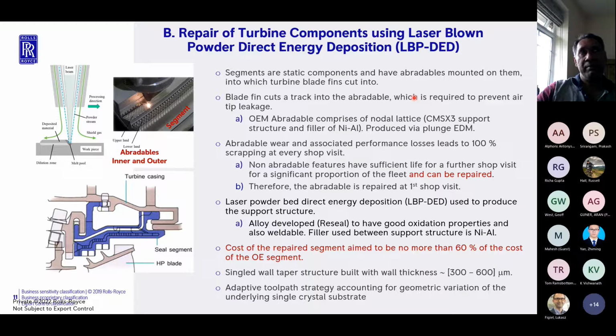So seal segments are typically components that are static. So these do not rotate like turbine blades. And really the main function of a seal segment is that the seal segment has got an abradable. So if you see a schematic diagram that I have here, this whole structure is the segment, and this is a blade. So the blade actually extends further down, but these two protuberances are the tips or the edges of the turbine blade. So these blade fins cut into the abradable. So this is one abradable, that's the other abradable, and these blade fins cut a track in the abradable as this blade begins to rotate.